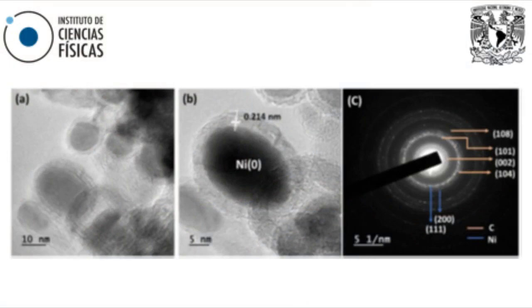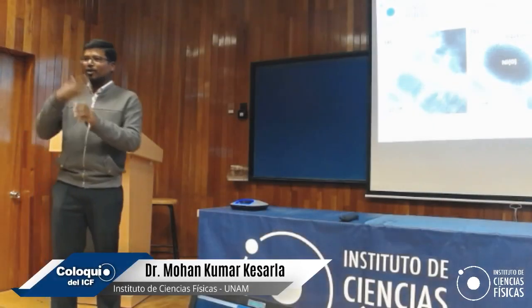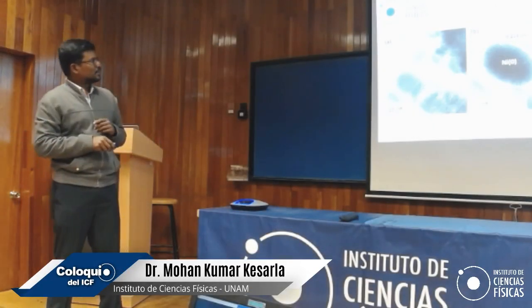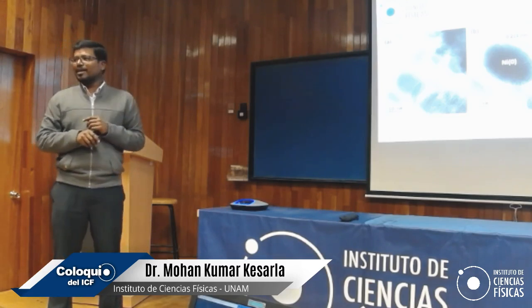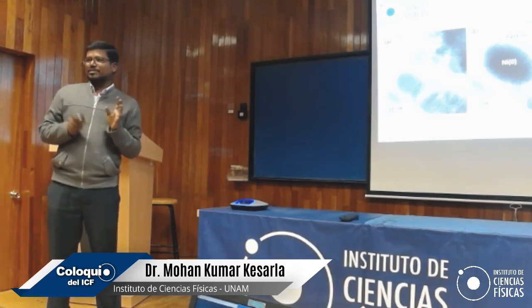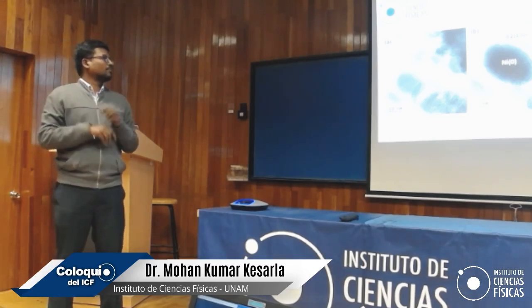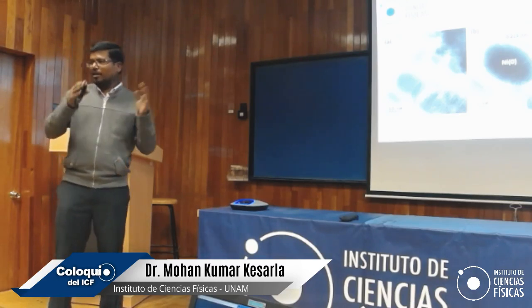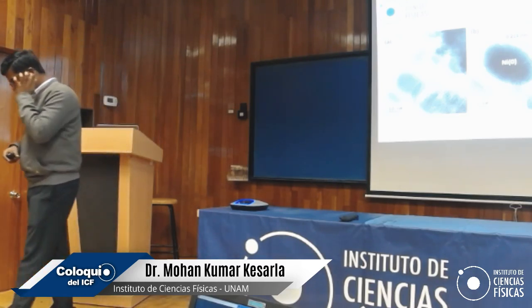What we noticed is the formation of carbon layers on the nickel, and it is extremely different. In our observations, and I didn't show the actual XPS or EDS, these layers don't have nitrogen. All the nitrogen escaped, and there is only a carbon layer, and the spacing of the carbon layer is very hexagonal, which is very different from our expectations.